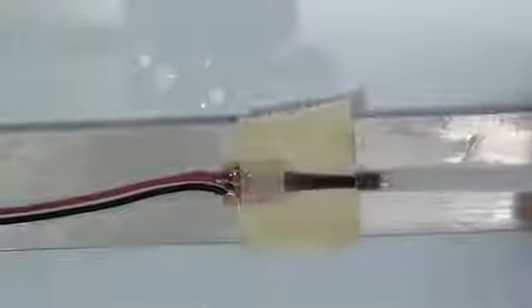We want to be sure that we remove all traces of that flux because, you know, one of the tests of an installed strain gauge, kind of a quality check to make sure everything is good, is we measure the insulation resistance of the installed gauge. Insulation resistance is the resistance from the lead wire system to the aluminum, the conductive. We want to see at least 10,000 megaohms there.